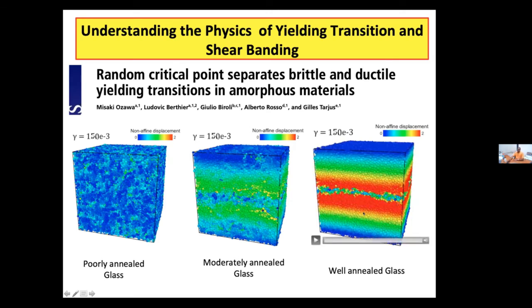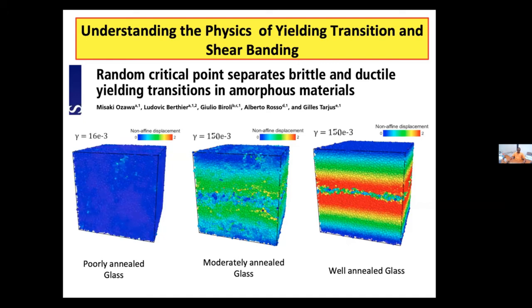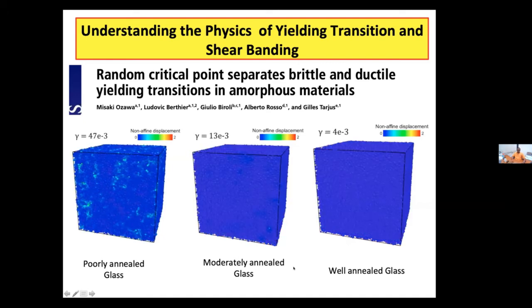And this is exactly what happens in our real glasses. When you look at real glasses or window glasses, and we hit it with maybe a hammer, it shatters. It shatters because it forms cracks, and cracks are a manifestation of these shear bands. So this shear band formation in this kind of clear format wasn't available to us, to understand the microscopic details of shear band formation. And thanks to Swap Monte Carlo, now we can go and understand it. And if we understand, maybe in future we'll be able to actually stop this shear band formation, and that can lead to better design of glasses.